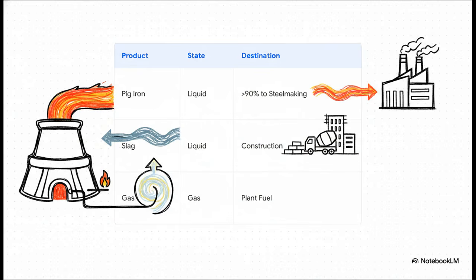And this is where you can really see just how smart the whole modern process is. Seriously, nothing goes to waste. Over 90% of that liquid pig iron goes straight to a steel mill to be refined. The liquid slag is cooled and then used to make things like cement and concrete. And that leftover furnace gas, it gets captured, cleaned, and used as fuel to heat the very air that gets blasted back into the furnace. It's this incredible, self-sustaining loop.